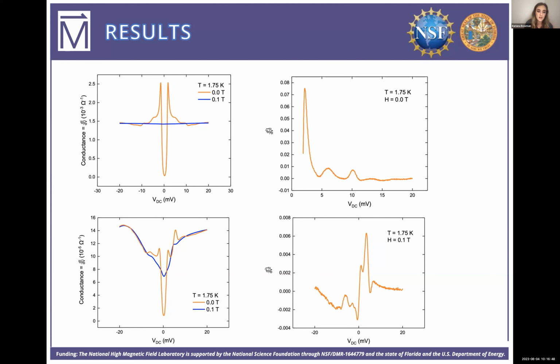So in the bottom left, the orange line is the samarium hexaboride and lead tunnel junction. There are some peaks here that we don't fully understand and that are a little different than the aluminum lead tunnel junction. And then the blue line is again when we apply a magnetic field and drive the lead to be normal. And then in the bottom right, we have that second harmonic measurement again, which is really what we were after. We have a lot of peaks here that we don't fully understand. And so the goal is to understand these more, but this is a new measurement. We're really excited because this is helping us characterize the material and hasn't really been done before.